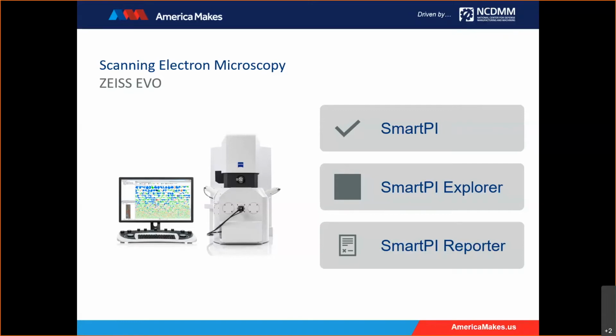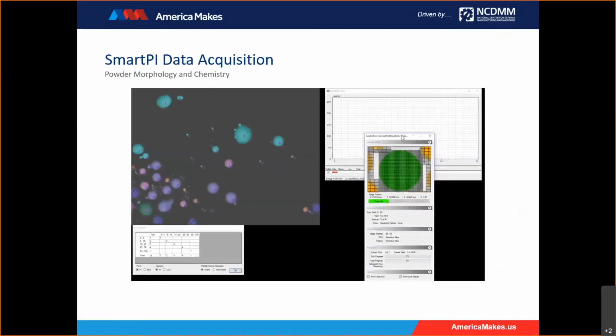SmartPI is a fully featured solution. It incorporates all the aspects of SEM control for image acquisition, it does image processing, and EDS elemental analysis for product characterization. So let me orient you to what SmartPI looks like in action. On the left, we have an image tile window with particles. The EDS spectra window is in the upper right-hand corner. And in the center, we have a general acquisition status window showing a schematic of the stub in green.